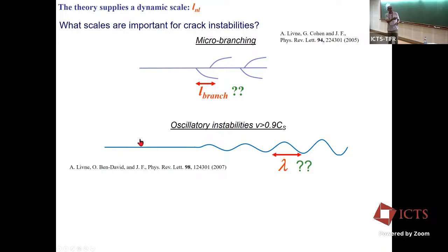These are tiny little branches, they're small themselves, but they increase dissipation by an order of magnitude. So if we don't know about them, all of a sudden we find that a crack dissipates more and more energy for basically no reason discernible to the eye. That's a macroscopic effect. The microscopic effect is, for example, this instability. What causes this instability is something even more microscopic, this very small region of elastic nonlinearity near the crack tip. So that's where we're going tomorrow.